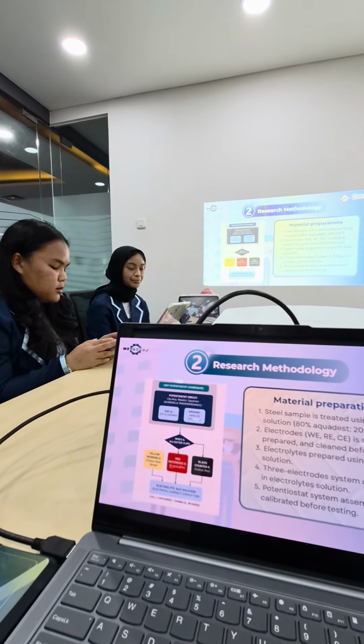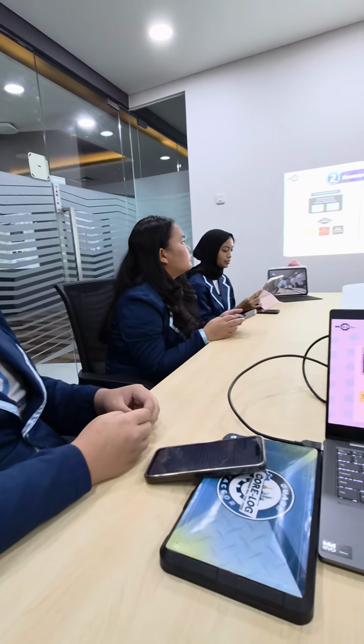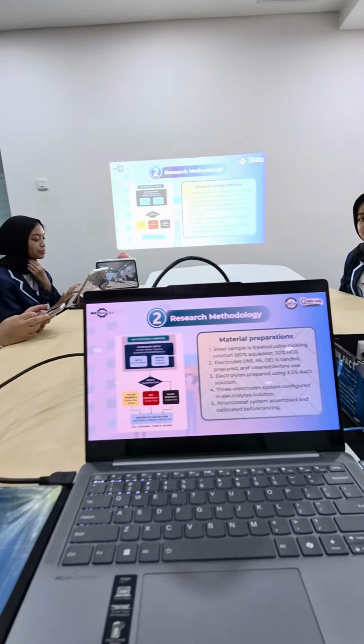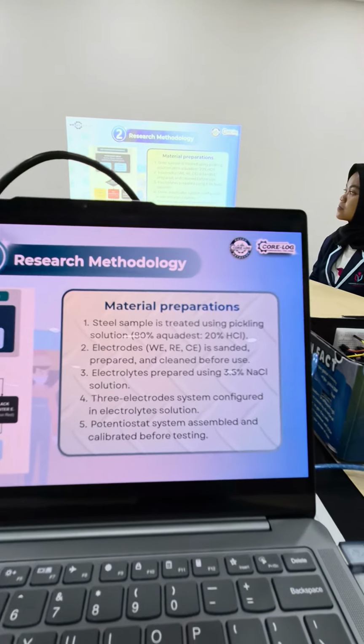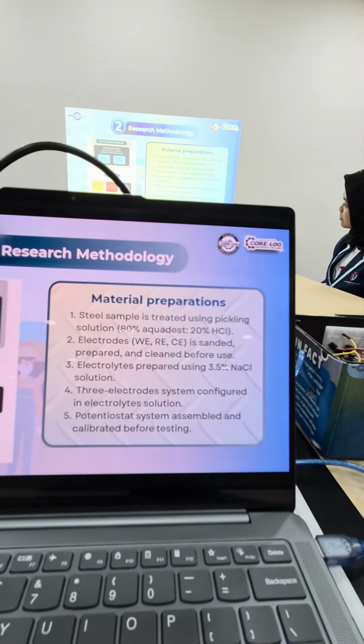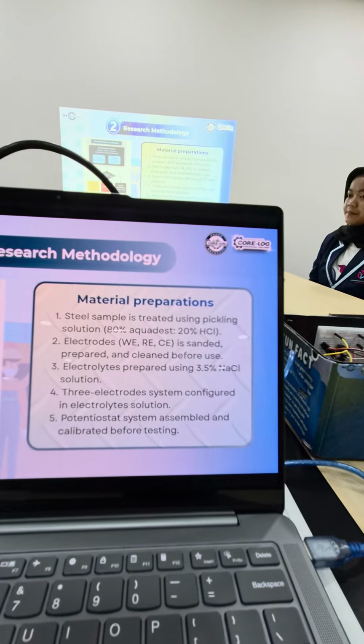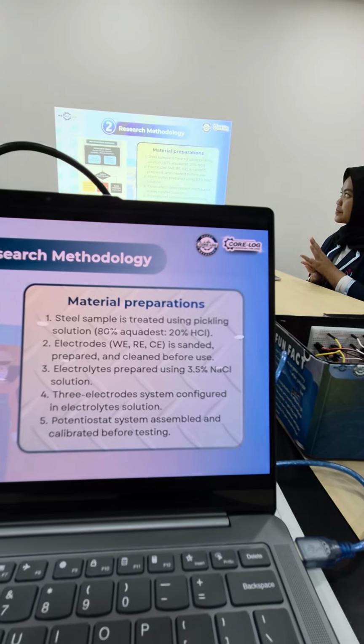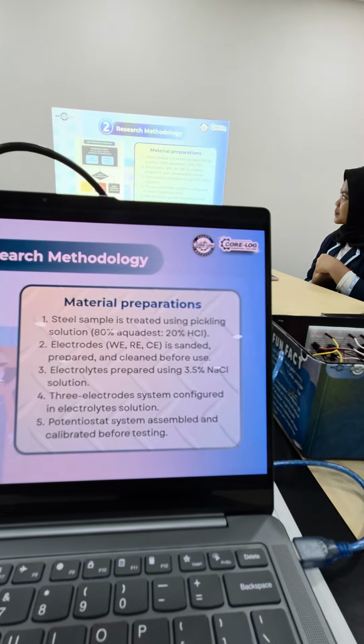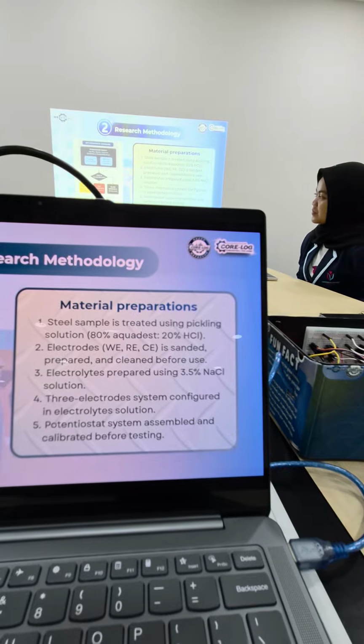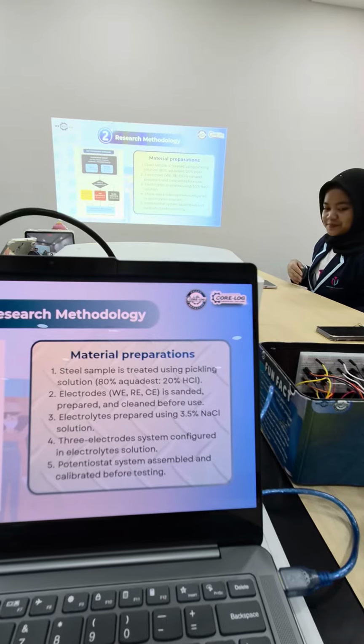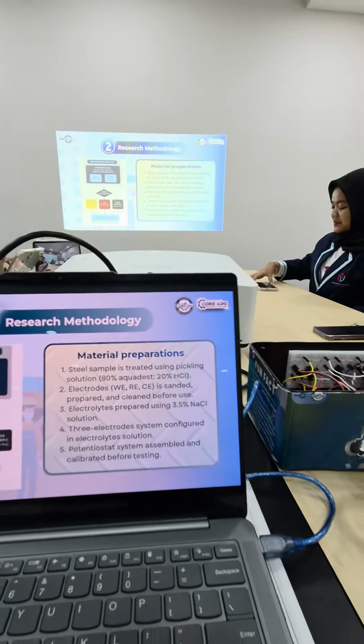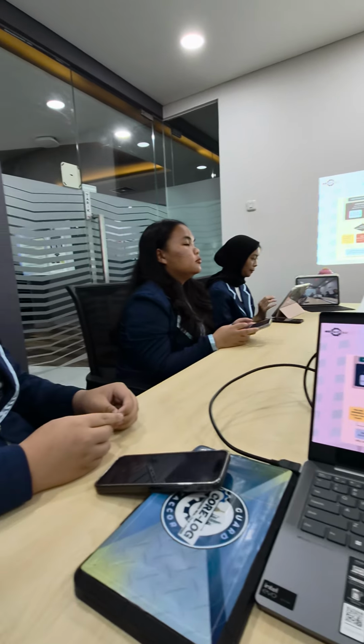Okay, next. For the material preparation, first, the steel sample is treated using the pickling solution with the ratio of 80% aqueous and 20% hydrochloric acid. Meanwhile, the other electrodes, which are the reference and counter, are sanded, polished, and cleaned before use. The electrolyte is prepared using 3.5% natrium chloride, and we use the 3 electrode system configured in the electrolyte solution. Before testing, the potentiostat system is assembled and calibrated.